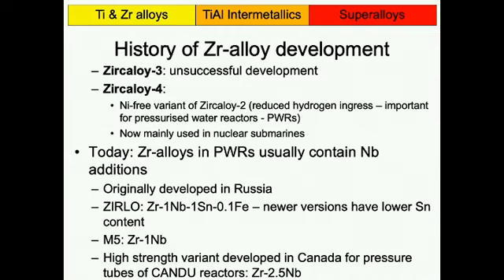So hydrogen pickup becomes an issue in PWRs, and it was found that nickel, it's generally the case that nickel is an element which can act like a window for hydrogen to get into material. So, for instance, nickel alloys can easily pick up hydrogen. However, in nickel-based superalloys, the hydrogen can't diffuse well, so that then limits maybe the hydrogen pickup. But in principle, hydrogen is very attracted to nickel. So that's why nickel was taken out for Zircaloy 4, and so it was possible to use this alloy then in PWRs.